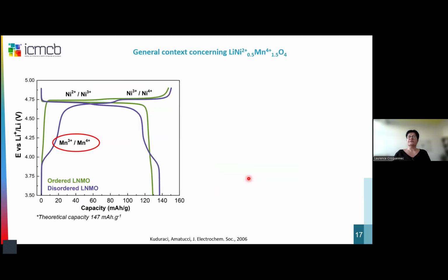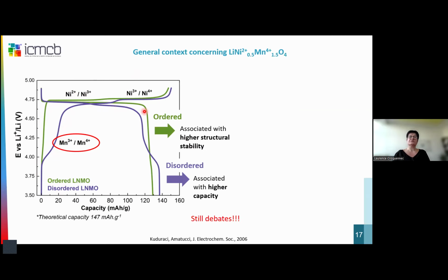Then, another information that is very important here is also that with the ordered LNMO, perfectly ordered, you have this green signature here. And so as you can see, only the involvement of the nickel in the reactions. Whereas when we move to disordered phases, we have the involvement of the manganese 3, manganese 4 redox couple, in addition then at higher voltage to, again, the nickel redox. But here also there are still debates. In the literature, we can find different statements about what is better, to have an ordered or a disordered phase.